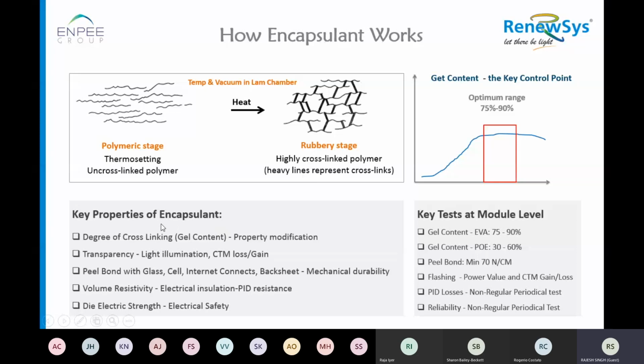A few basic properties of encapsulant which we control are the degree of cross-linking, by way of formulation and process, and transparency, again based on the selection of material and the process involved in making them in sheet form. We add some material which makes peel bond, or bonding of these encapsulants with cell, glass or backsheet, because encapsulant is the only material which binds everything together. It also provides volume resistivity, which gives PID resistance to the cell and complete module when it is made. And finally, dielectric strength is the electrical property of the module, which gives safety.